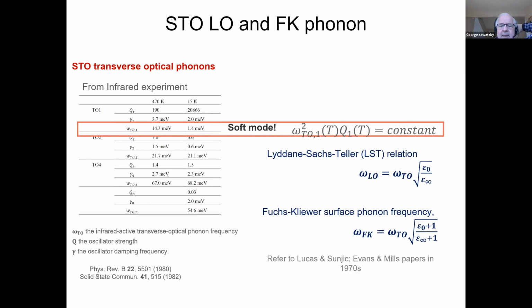It's from way back when in the 1970s, Fuchs-Kliewer and so on, they did this work on surface phonons, which basically in this case are the longitudinal optical phonons of the bulk, which are shifted a bit at the surface. Okay, and you can get everything just from the infrared data. We have no adjustable parameters. Everything comes from the infrared data, where we have all of the phonon frequencies. And I'm going to talk specifically about this one.